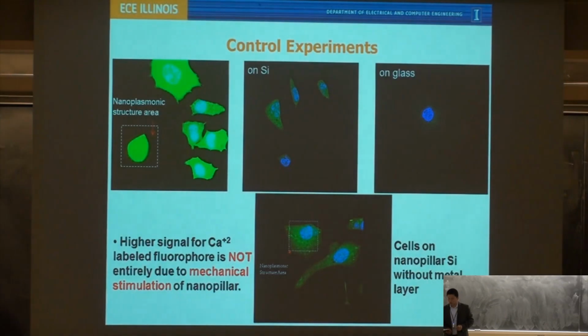All right, so we also did some control experiments to exclude the factor that the cells may just behave differently when they are on the nanostructures, which is my second topic that I will touch upon very quickly. In our control experiment, this is on silicon-based nanostructures without a metal layer. You can see on silicon you still have some nanostructure here, and we don't see any enhancement. So the enhancement does come from the metal. If you don't coat metals, you don't have the enhancement. On the glass, the fluorescent intensity is even weaker because silicon is a little more reflective than glass.